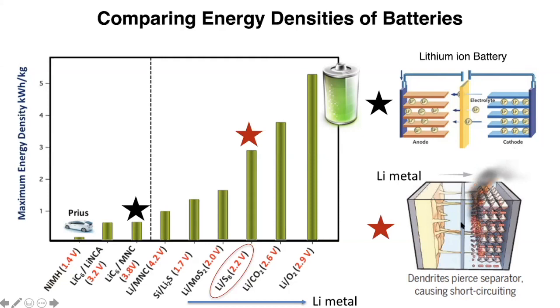And then the dendrite can penetrate through the separator. And if it penetrates through, lithium metal is conductive. If it touches the cathode, then it will short. If there's a shorting in the electrical circuit, what happens? It heats up. Once it heats up, the electrolytes are flammable. Then they catch fire. And that's when you hear in a lot of the news that a lithium battery catches fire. Well, that's not yet using lithium metal. That's just graphite based, but you can have defects that cause the dendrite to grow.